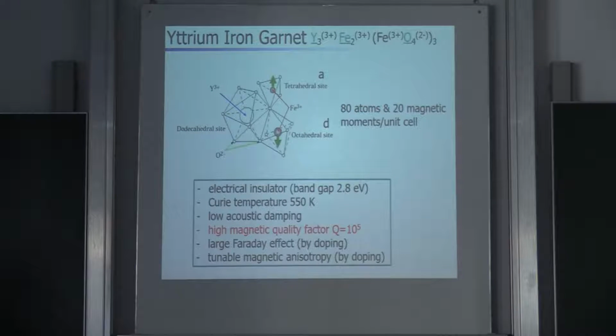Now it's a very good electrical insulator with a large band gap. It has a very conveniently high Curie temperature. And we will see it's important that the acoustic quality of YIG is very good. So it's the same order as quartz, for example, which is used in your watches. And most important, it has a very high magnetic quality factor. So that means if you excite the magnetization, it will go on for a long time before it is being damped out.